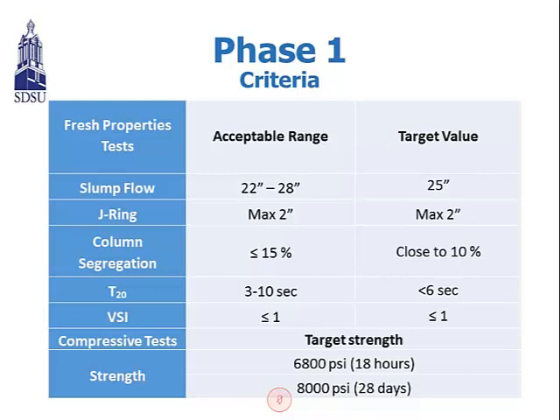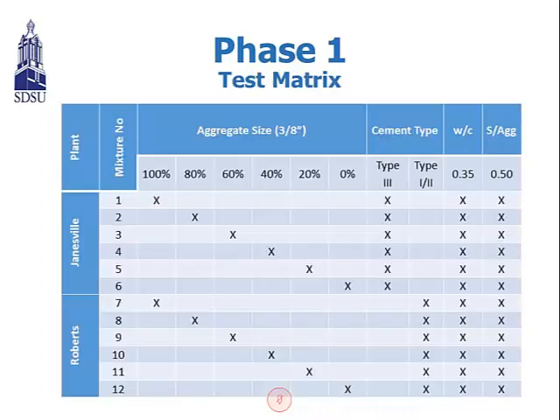So slump flow is established with an acceptable range of 22 to 28 inches, and a target value of 25 inches. J-ring must be less than a maximum of 2 inches, and column segregation must be less than 15%. The T20 time is at 3 to 10 seconds, and the target value is 6 seconds, and the VSI must be less than 1. The compressive strength targets are 6800 psi at 18 hours and 8000 psi at 28 days, as I mentioned before. And here's the test matrix.